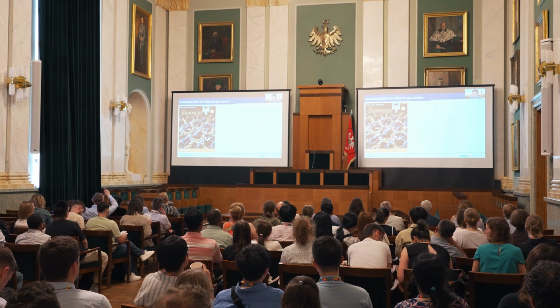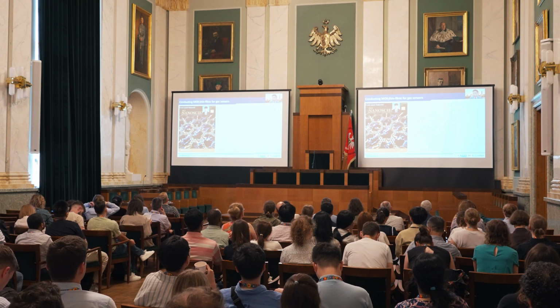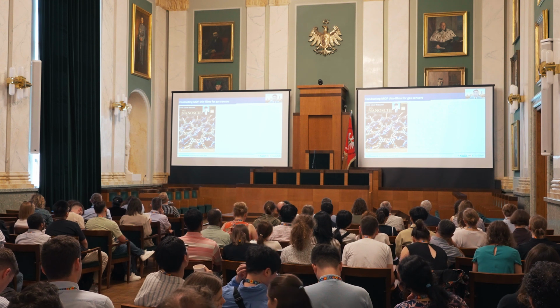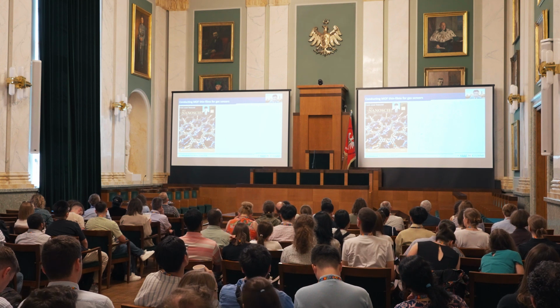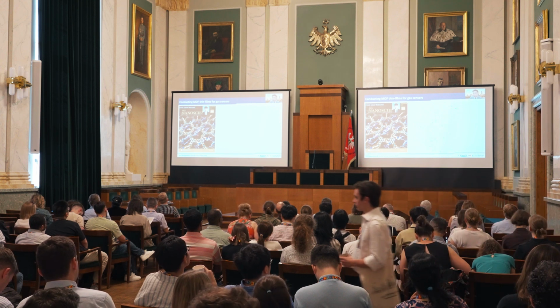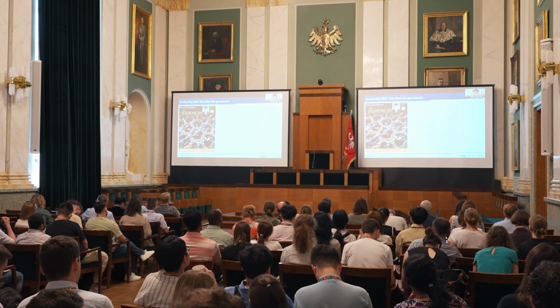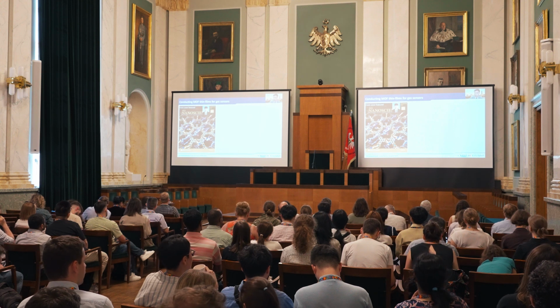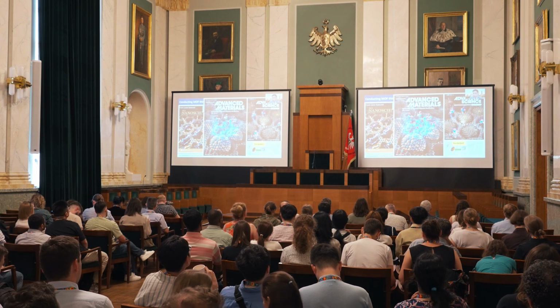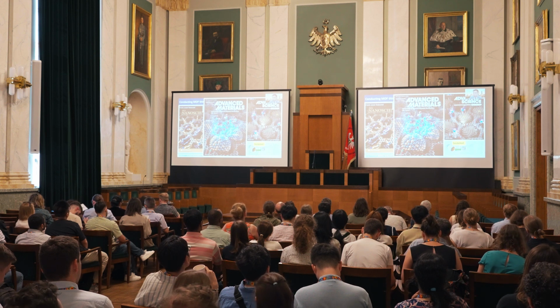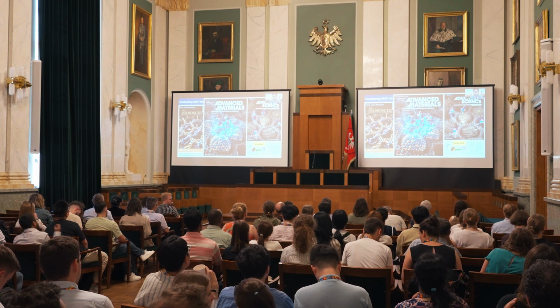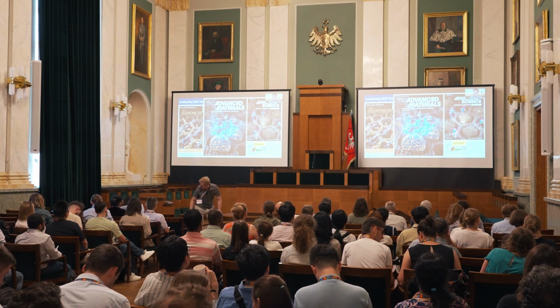Let me show you 2 examples. The first example is the metal organic framework. The MOF consists of a metal node and an organic linker, and this is a conducting MOF. It has high porosity and high surface area. So we can simply infiltrate the metal ion into the inner cavity, followed by a simple reduction process. We can synthesize small catalytic nanoparticles that look like a bulb structure, socketed structures. For example, platinum particles and palladium nanoparticles. And also, once we introduce 2 precursors at the same time, then we can create a bimetallic nanoparticle.